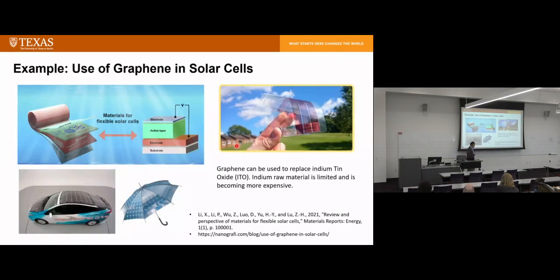For example, you can use graphene in solar cells. Solar cells are very important for energy harvesting. If you can roll it up, there's a huge market for solar cells. In a solar cell, there are top electrodes and bottom electrodes, and in the middle, there's active material. When sunlight comes in, the photon energy strikes out the electrons, so you can collect the charges to generate electricity. The top layer is very important. That layer has to be optically transparent to allow sunlight to pass through, and it also has to be conductive.